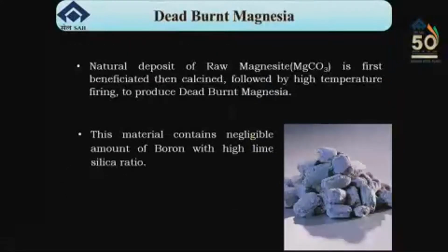Third one is dead burnt magnesia. The natural deposit of raw magnesite is first beneficiated, then calcined, followed by high temperature firing to produce dead burnt magnesia. This material contains negligible amount of boron with high lime silica ratio.